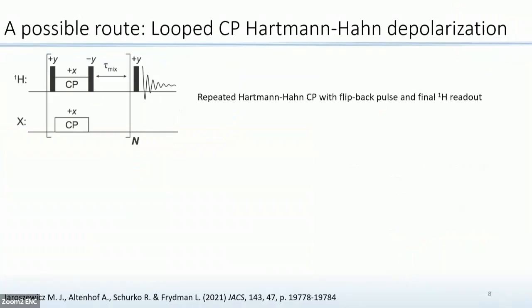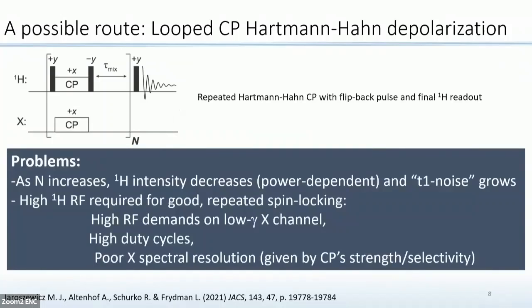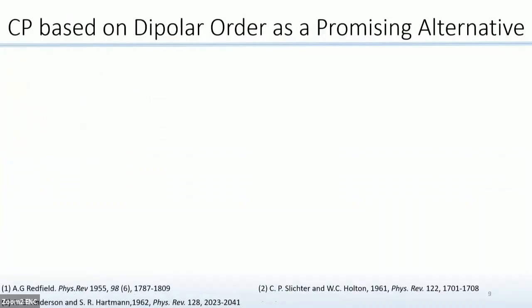So the first type of sequence that we thought might be able to work was repeated Hartmann-Hahn CP with a flipback pulse and then a readout. But this version of the sequence had a few problems, namely that it required high RF on the protons to get good spin locking. Otherwise, we suffered from a decrease in the intensity because of generation of higher order coherences. And in turn, the high RF on the protons had a few problems. We had to match it with high RF on the X channel, which is typically not possible for low gamma. Then it would also require very high duty cycles. And finally, our goal was to perform indirect detection, so this would result in very poor resolution.